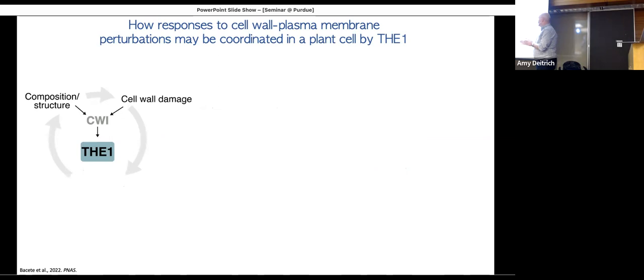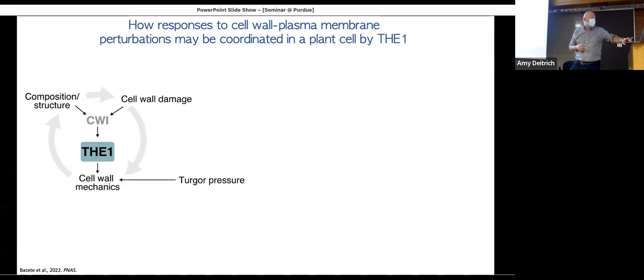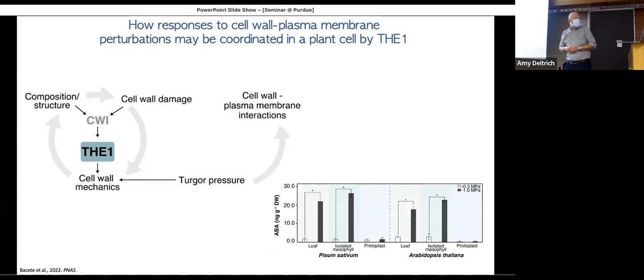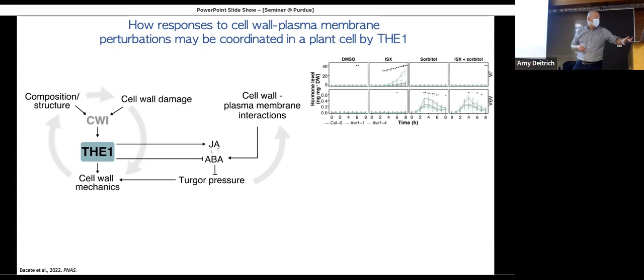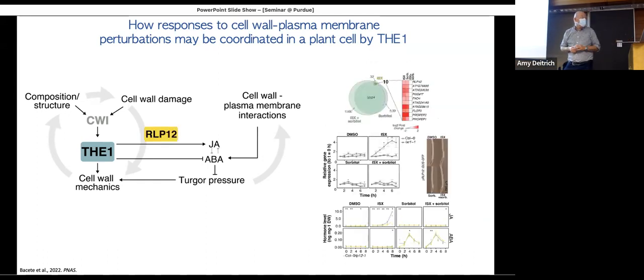So when you think about cell integrity, as far as we can tell, it's influenced by compositional structure, but also by cell damage. And we think that THESEUS1 has a key function there. This function means also that it is modulating the cell wall mechanics. And this is the result of the stiffness measurements that we've done. What we also think is that turgor pressure influences cell wall mechanics. Again, the results from the stiffness measurements. We do know that the cell wall-plasma membrane interactions are really important for the induction of ABA, which brings ABA into play. And at the same time, we've shown that ABA is repressed by THE1 action, and that THE1 is required for JA induction. And last but not least, we've introduced RLP12 as a new player in cell wall integrity maintenance.